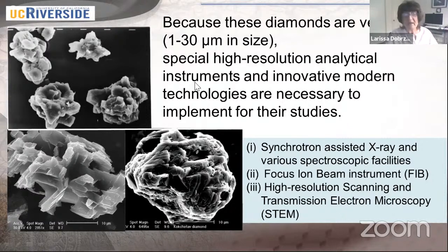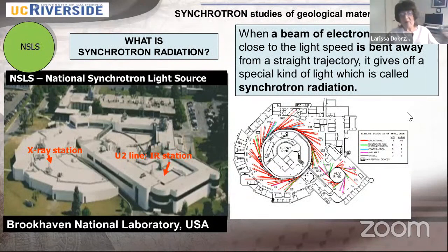So technologies came: synchrotron-assisted X-ray and spectroscopic facilities, and the focus ion beam instrument, which allows you to cut a very, very thin sample, which we call foil, to be studied at high resolution by scanning and transmission electron microscopy. So now I would like to stop on these techniques, because the study of inclusions by these techniques does not take a lot of time. It's usually hours, even sometimes minutes, especially with synchrotron radiation. However, preparation of samples and understanding what you're going to do with them takes months, a lot of time. So I prefer to remind my audience what this technique means.